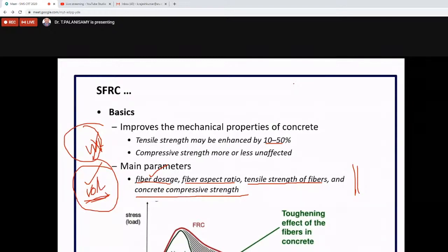So what is the need to control the fiber dosage? If you add more fiber into the concrete, the first problem is the balling effect. The fiber is sticky, needle-like in nature. It easily tends to bend. It is unable to flow easily into the concrete. It takes or absorbs the concrete and makes it into a ball. It keeps rotating like this. It is not easily dispersed throughout the concrete. So control of the fiber dosage is a must.